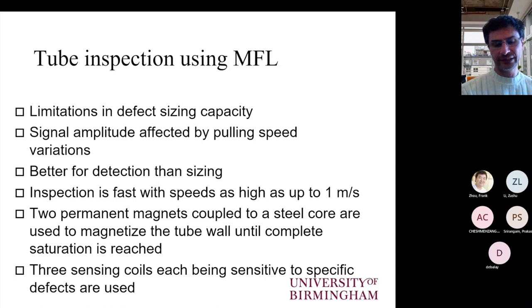And the effective instrument is based on two permanent magnets, which are coupled to a steel core, and then they are used to magnetize the sample or the tube wall until saturation is achieved, and then any flux leaking will be what will be detected. In tubes, we have to use three sensing coils. One is the absolute coil, and the other two are the differential coils. The absolute coil is designed to detect general corrosion. The differential coils are designed to detect pitting corrosion and are more sensitive to smaller defects.